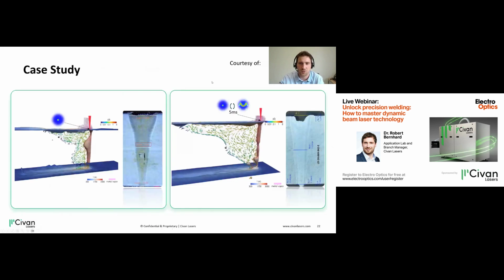This actually is also really interesting, and something we observed is that by lasing with just a single beam shape, we get a lot of cracks, especially in thicker material. And doing the different shape and another shape, it's also a problem that the cracks are still there. And the only solution is to do the alternation between two different beam shapes, and then all of a sudden it becomes good, so that we have no cracks, no inclusions. And so there's a way of keeping the keyhole open, as well as making sure that weld penetration is just right.